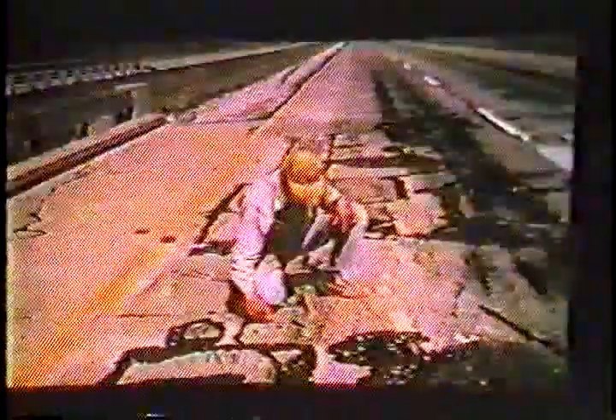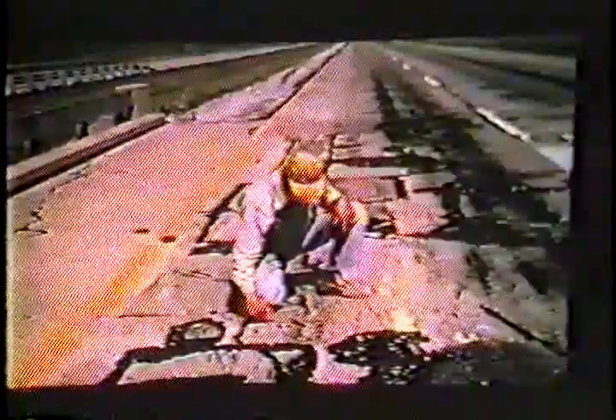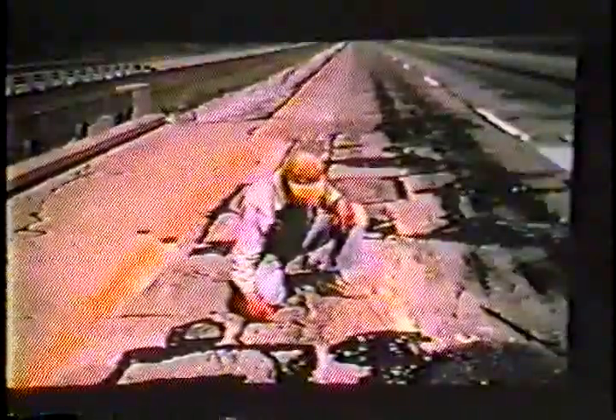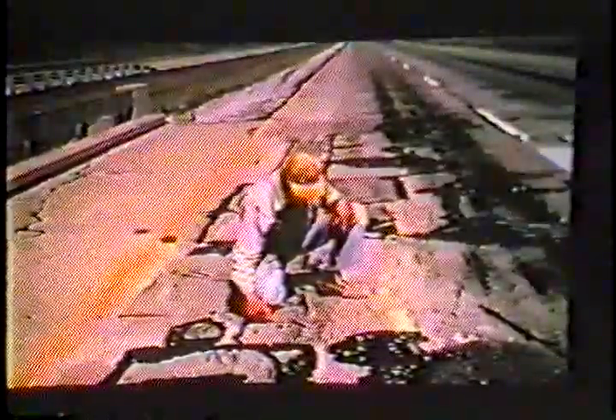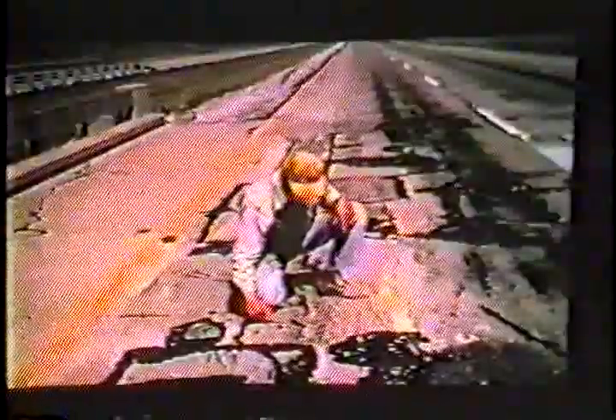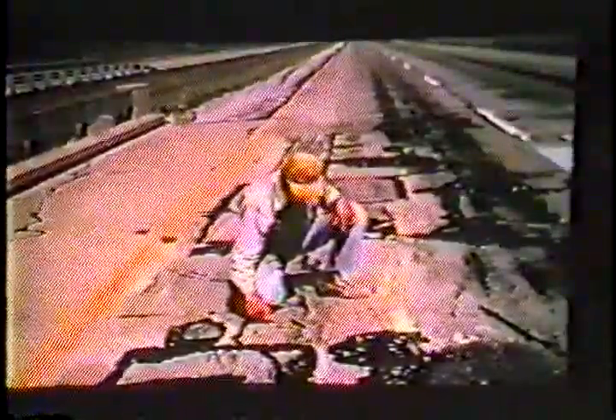Therefore, early repairs to deteriorated areas should be made. This requires sounding with a hammer or other method on the concrete deck to determine the area to be broken out. On asphalt overlays, you may need to do some guessing, but sounding will give a fairly accurate determination. It is very important that we repair the fractured area as well as the pothole. If we don't repair the adjacent loose concrete, we will soon be back.